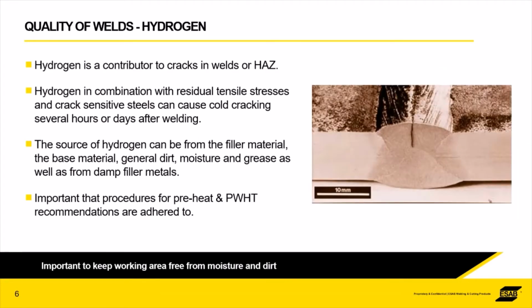So hydrogen is a source of cracking. Hydrogen is created, it can be from the base metal, if the base metal is particularly dirty, contains moisture and grease. The moisture will break down and create hydrogen gas. Hydrogen gas is certainly a contributor to cracking in the welds or the heat affected zone. So to get rid of the chance of moisture, that's why preheat procedures and post-weld heat treatment procedures are absolutely recommended to be adhered to.